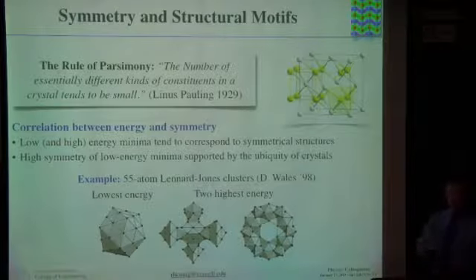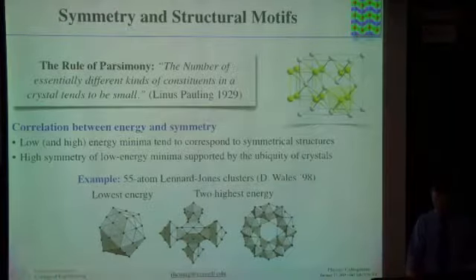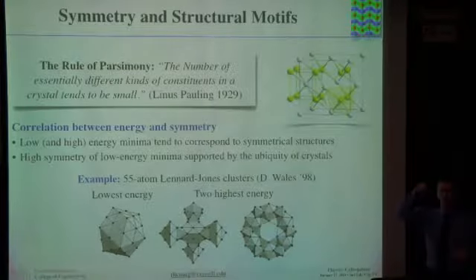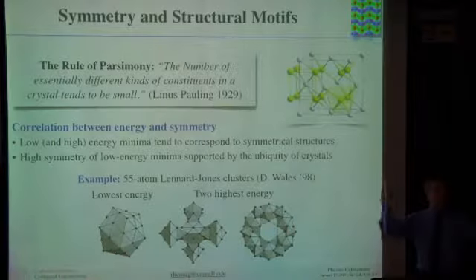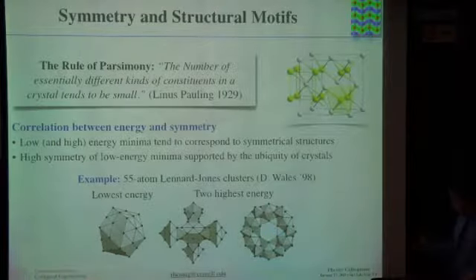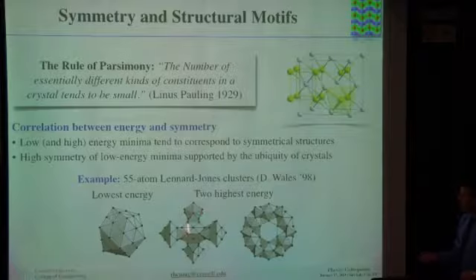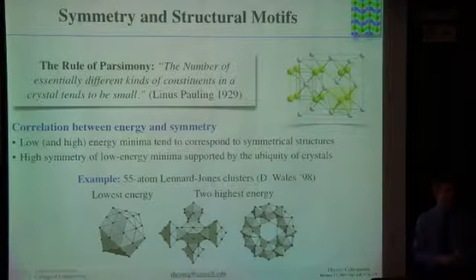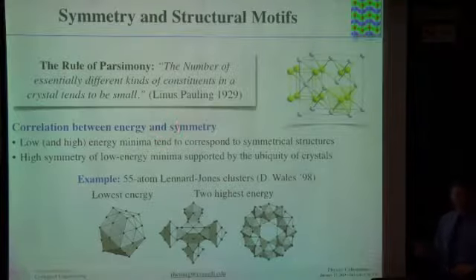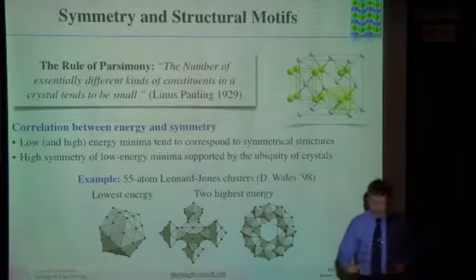And if you look at the highest energy structures, that's somewhat interesting. These are stable structures. You try to come up with the Lennard-Jones potential with structures which are locally stable, so they're minima, and you try to come up with what's the worst you can do. You end up with these two structures here, which also have a lot of symmetry. It's immediately visible. That was actually something I found somewhat surprising. But so symmetry helps. So we often have to look for symmetric structures.